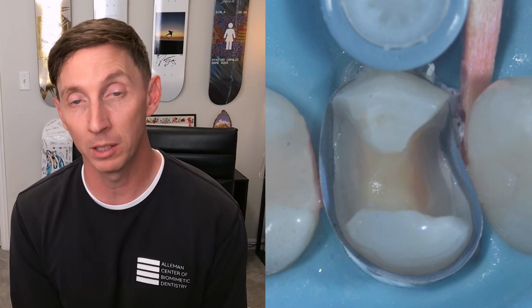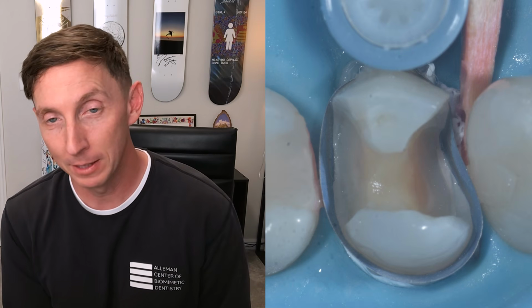I'm going to say that again. The bond to dentin can exceed the cohesive strength of enamel, which is around 30 megapascals. But the only way to do that is to allow these slow maturing bonds enough time to develop before we start to layer with our restorative material of choice.